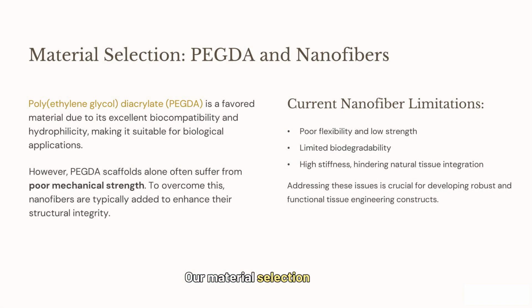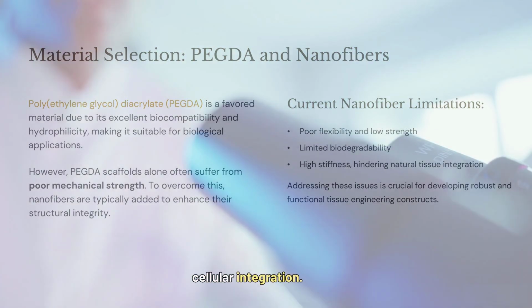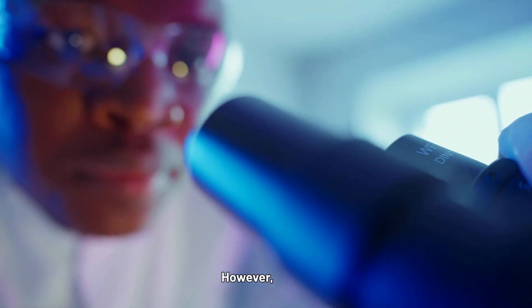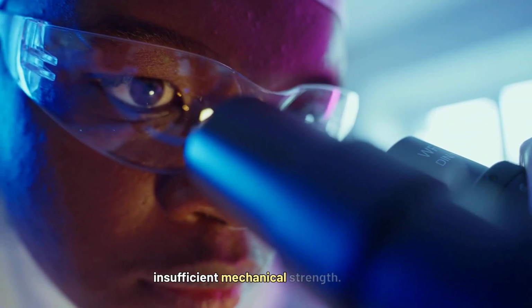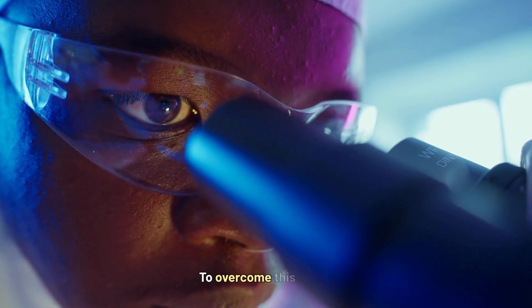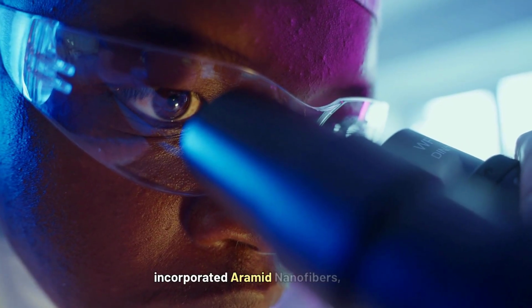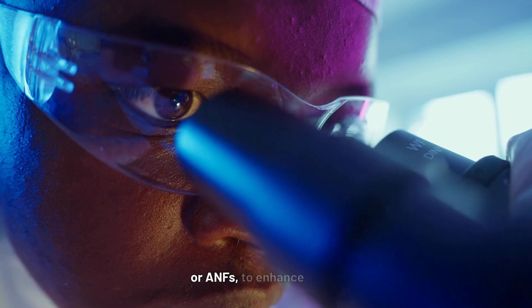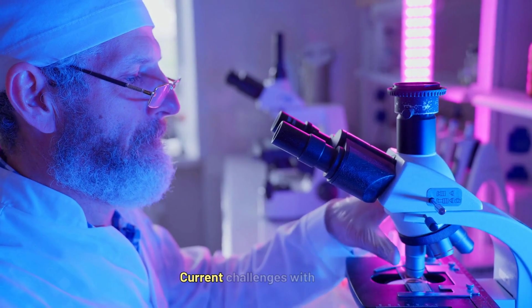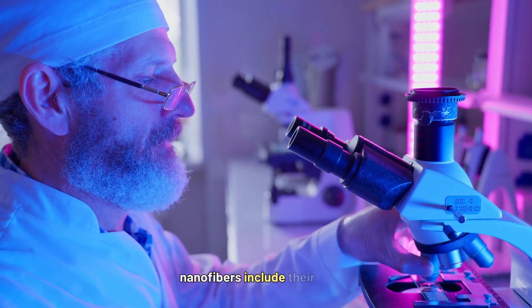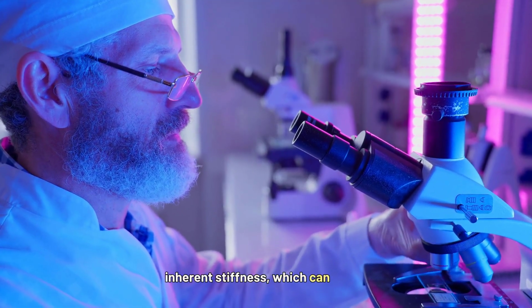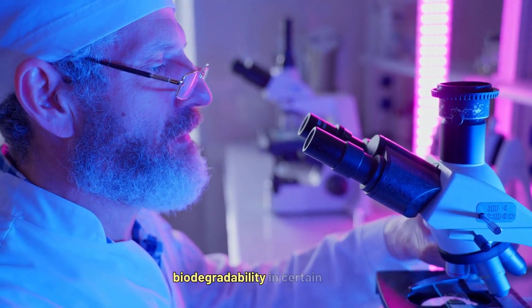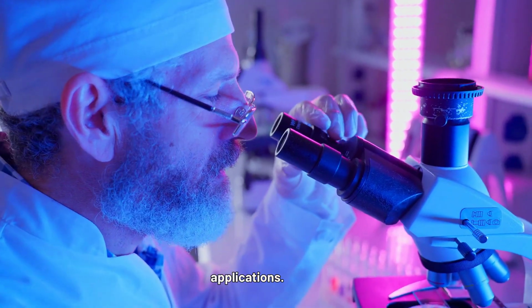Our material selection focused on polyethylene glycol diacrylate, or PEGDA, due to its inherent biocompatibility and hydrophilicity, which are crucial for cellular integration. However, PEGDA alone exhibits insufficient mechanical strength. To overcome this limitation, we incorporated aramid nanofibers, or ANFs, to enhance structural integrity. Current challenges with nanofibers include their inherent stiffness, which can limit flexibility and biodegradability in certain applications.